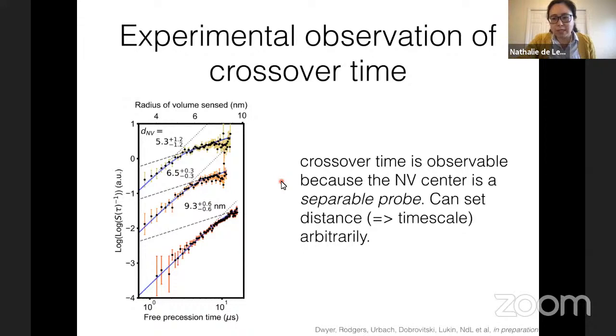Everything that I've told you about is a generic feature of disordered spin ensembles, and you should be able to see this in principle in things like ensemble NMR and ensemble ESR. But the key difference here is that this crossover time is set by the closest distance between spins that's possible. In a normal solid, that's going to be at lattice constant scaling, so it's very hard to see this time scale. Here, because the NV center is a separable probe, we can set this distance arbitrarily, and that allows us to set this time scale arbitrarily. So it's a feature of this nanoscale sensor being different from the stuff that we're probing that lets us see this physics.